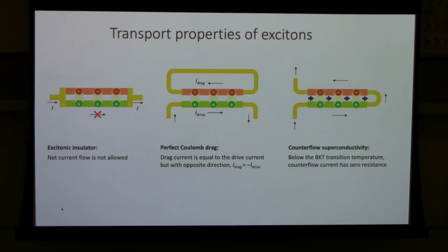then the exciton means the electron and hole will move in the same direction. So there will be an electron charge density moving in the same direction. But because electrons carry opposite charge, it corresponds to an electrical current that moves in the opposite direction, but with the same magnitude as this drive current. Another way people do this is the so-called counterflow measurement. In this case, you pass opposite currents in the two layers, which corresponds to excitons moving in the same direction. If you have a superfluid, then it will be a dissipationless current flow. If you measure the potential drop in this hole layer, you'll find there will be 0 voltage drop.